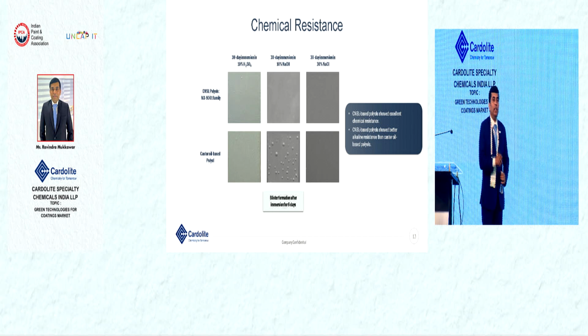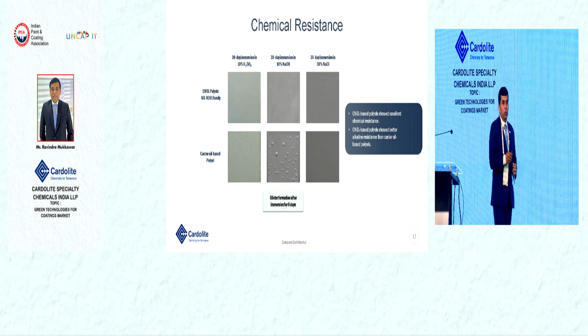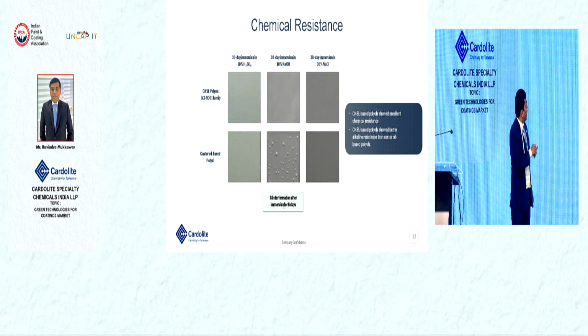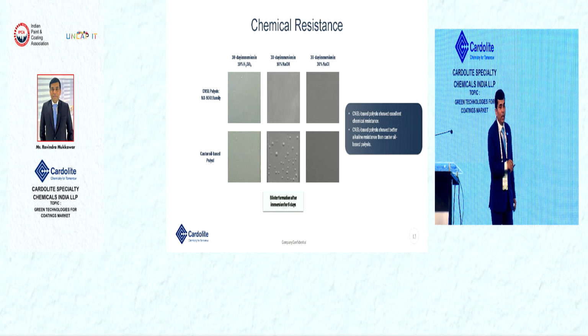So this is a less moisture sensitive product. Another advantage of our CNSL based polyol compared to other polyols like castor is good alkali resistance. We checked a 30 day immersion test with H2SO4 and sodium hydroxide, but after 6 days, the castor based polyol gave blistering. So this is another advantage of our CNSL based polyol.